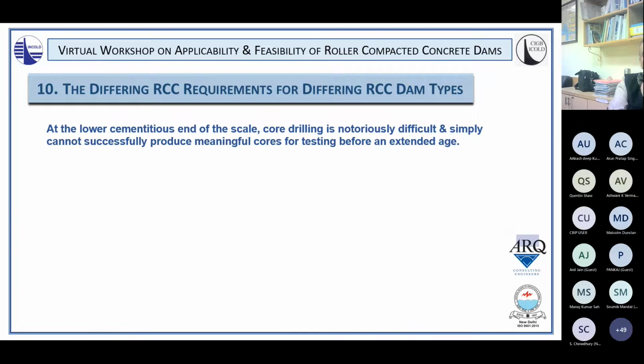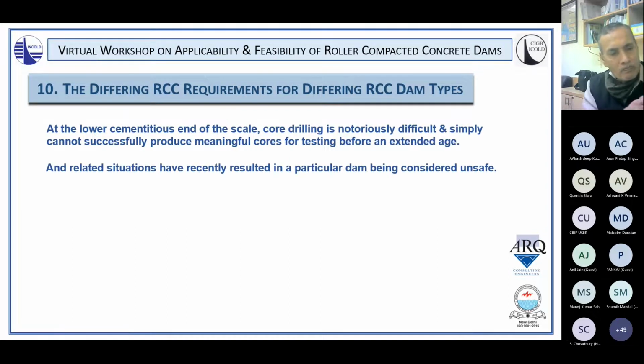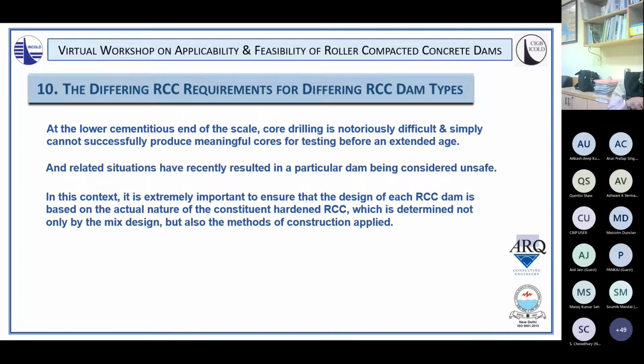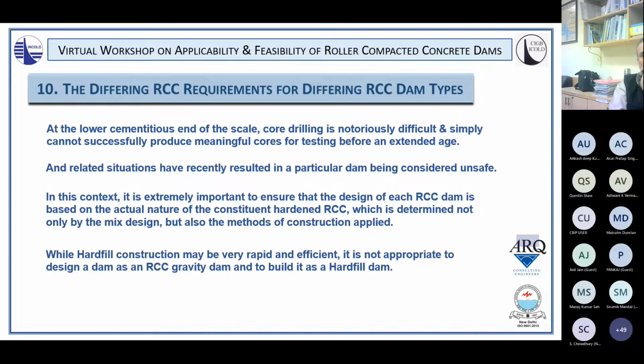At the lower end of the cementitious scale, core drilling is notoriously difficult and simply cannot successfully produce meaningful cores for testing before an extended age. So you cannot design a concrete with very low cementitious materials, drill within a couple of weeks and expect to see what the shear strengths of that concrete will be. And related situations have recently resulted in the particular dam being actually considered unsafe. And in this context, it's extremely important to ensure that the design of each RCC dam is based on the actual nature of the constituent hardened RCC, which is determined not only by the mix design, but also the methods of construction that are applied.